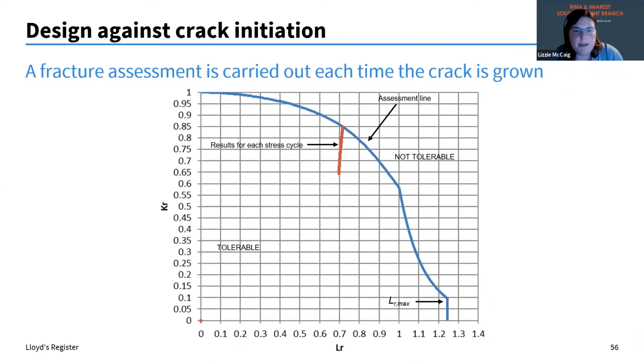And then we have an LR max, which is this cutoff point that we have. And you can see here we have results for each stress cycle, and then you stop the calculation when it hits this line, and that's where you hope that you've achieved enough life in your ship as compared to the design life of the ship that you don't have to worry about this defect. But obviously you take those defects and then you do enhanced NDE to actually go and measure all the size of the defects in the welds and make sure that they're not above that critical defect size.